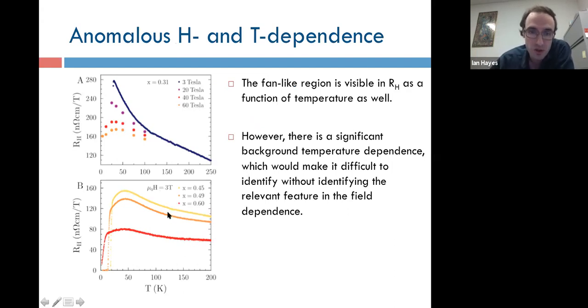If you look at the temperature dependent part, there's some slight temperature dependence at high temperatures. You see the upturn, this is the data you saw before, that can be suppressed with a large magnetic field. And if you go to the overdoped side, you still see the upturn, but it ceases growing at successively higher temperatures, so that by the time you're on the overdoped side, it still looks relatively flat. And it would be fairly hard to characterize this background well enough to measure this without the field.